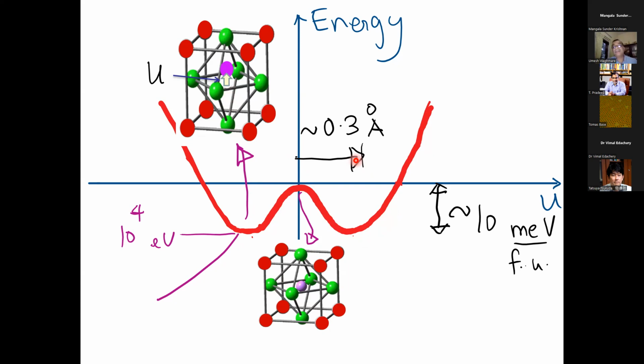What is spectacular is that typically these off-centering displacements in these oxides are of the order of 0.3 angstrom. And the total energies of these crystals are tens of thousands of electron volts typically. And this energy difference is very tiny, just 10 milli eV per formula unit. So you're looking at very tiny energy differences between two large energies that can be calculated from first principles. So you do need very accurate first principles calculation to capture such a phase transition. But this is the figure.